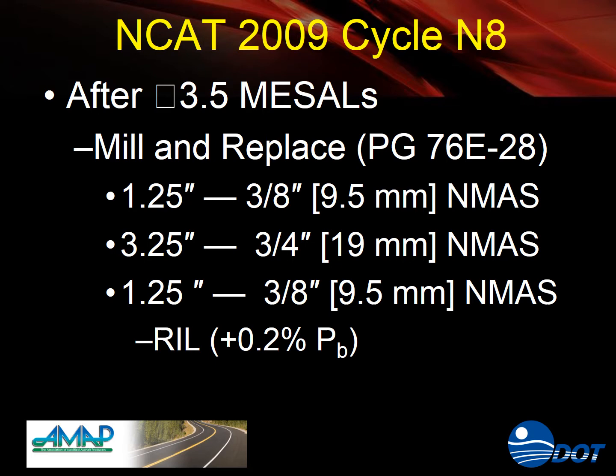You kind of notice that we're using this highly fine aggregate, which you normally wouldn't use as a surface course. And then we're also using it as a third lift down. And I call this rich intermediate layer, which is actually the same thing, only 0.2% more binder, essentially. VMA is increased accordingly.